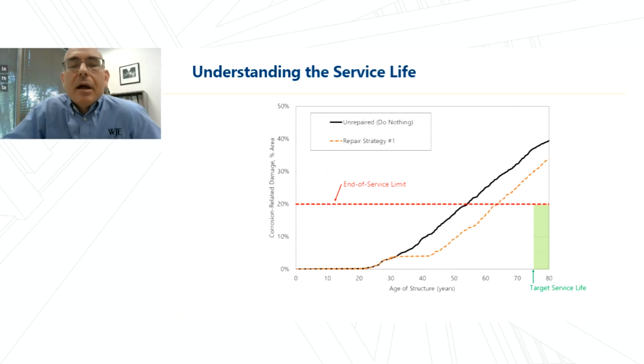So let's examine the scenario where the owner chooses to intervene in the deterioration of the structure after 30 years of age. And we'll call this repair strategy number 1, which is shown in the orange dashed line. It's the revised progression of deterioration of the structure after the repairs are instituted. You can see that repair strategy number 1 slows the rate of deterioration for a period of years, but then deterioration continues after that. And this curve also does not achieve the target service life, although it does extend the service life by about a decade.